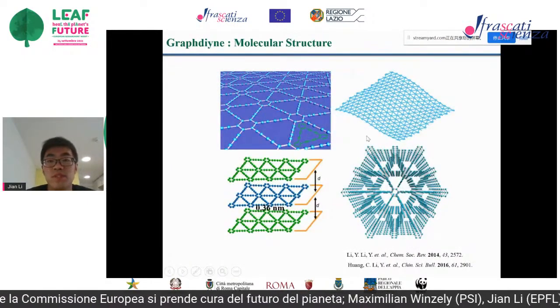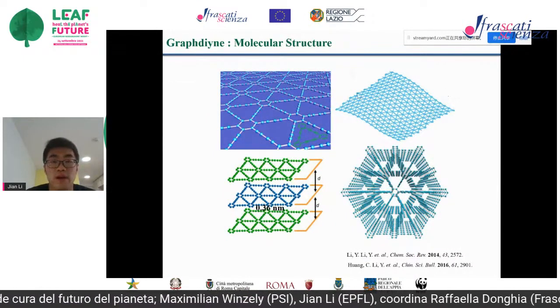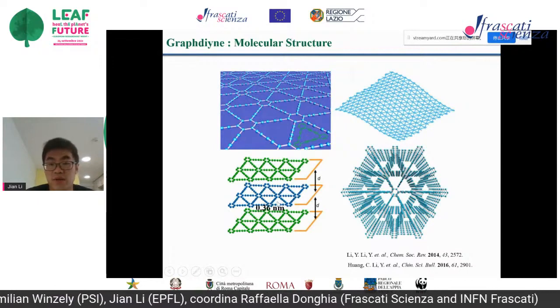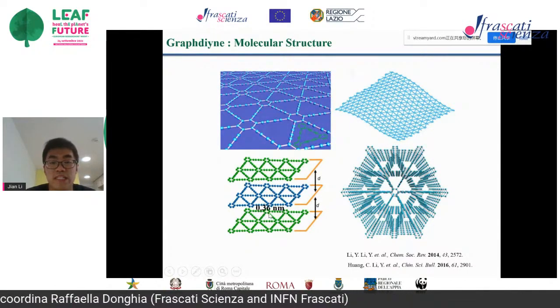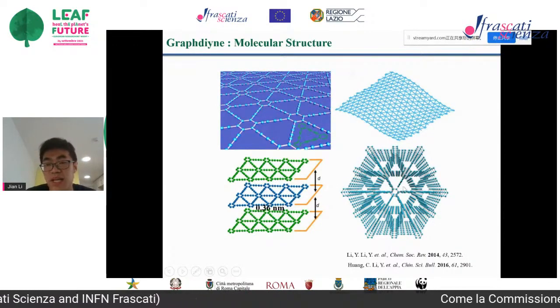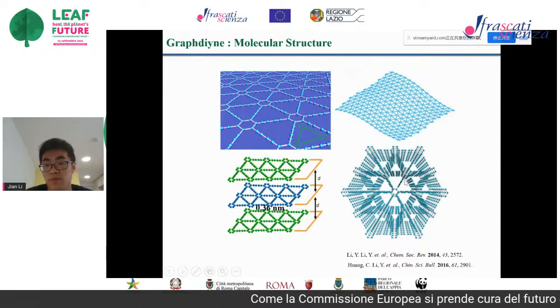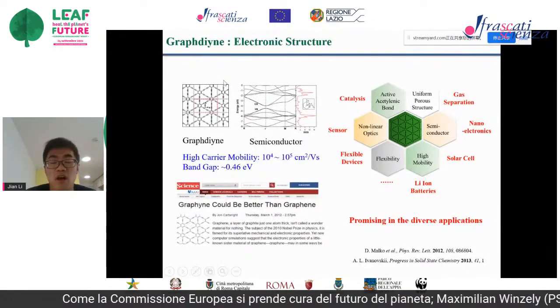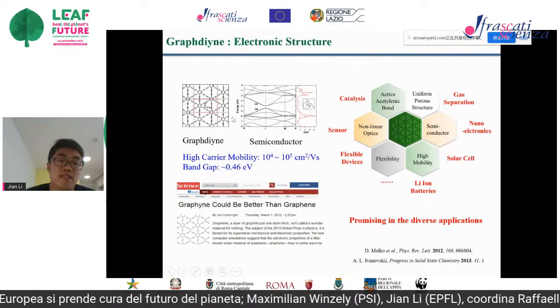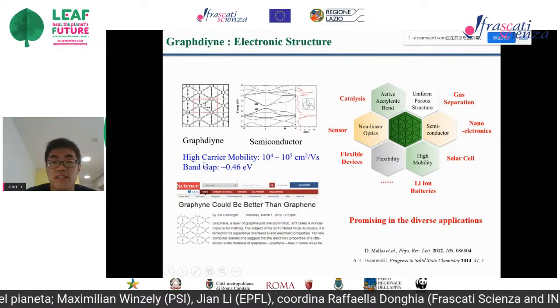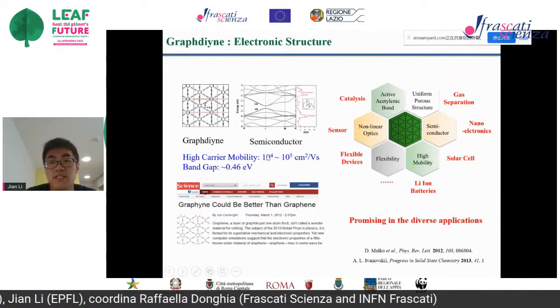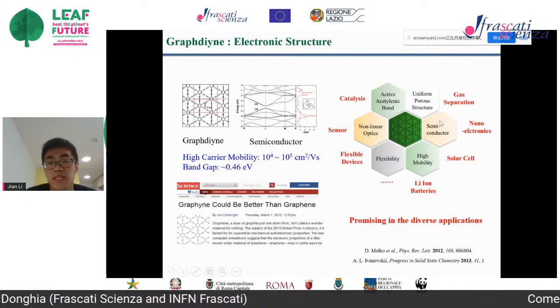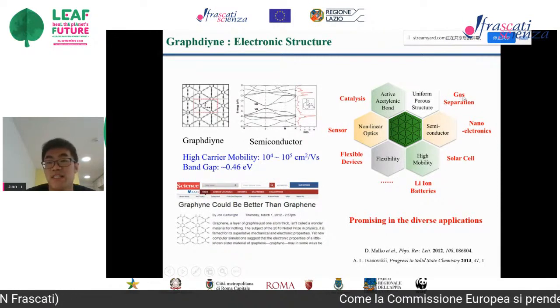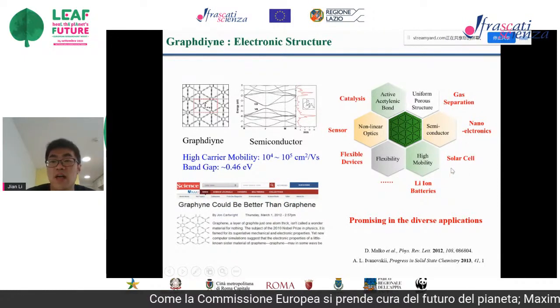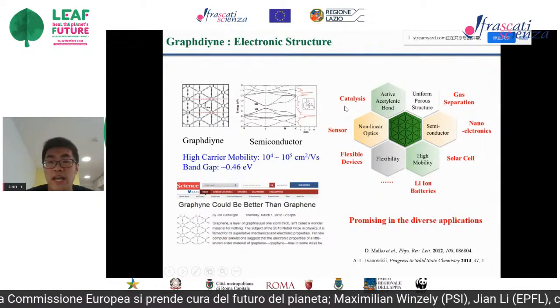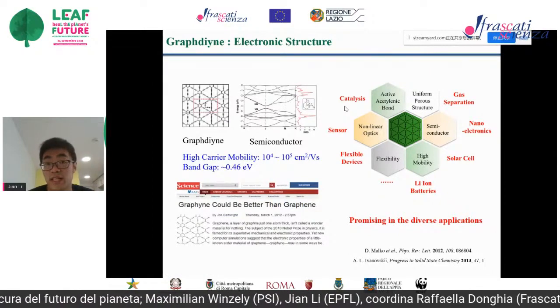We will introduce some structure and electronic structure properties of graphdiyne. Here we can see it is a layered structure, and the layer spacing is 0.36 nanometers. This is the 3-dimensional structure, and we can see uniform pores distributed on this material. Graphdiyne also has some excellent electronic properties, such as a natural band gap and high carrier mobility. These good attributes make it promising in diverse applications, such as gas separation, catalysis, sensors, solar cells, and so on. I will focus on graphdiyne in catalysis, especially photocatalysis and photoelectrocatalysis.